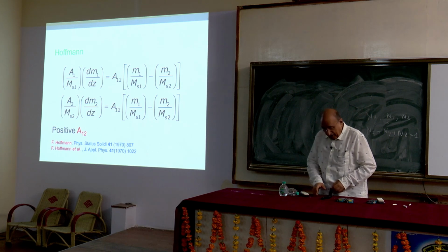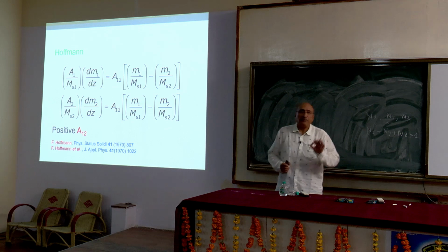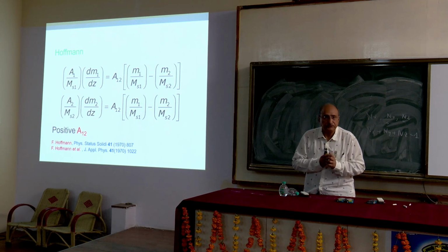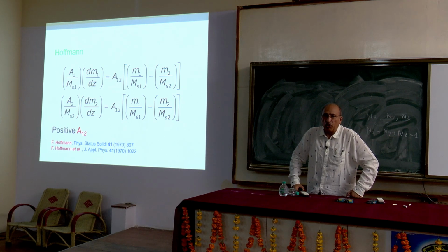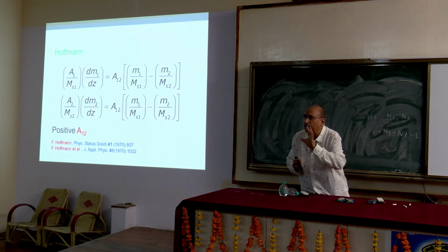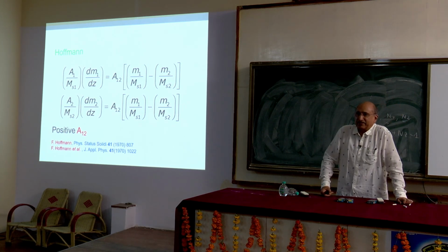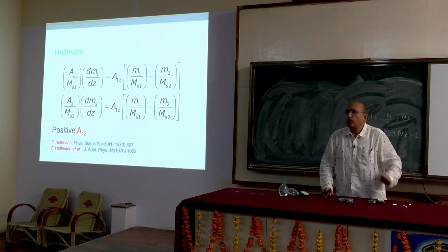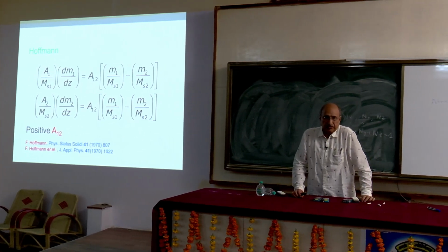which introduced another constant, A12, which is the interfacial anisotropy. Our boundary condition did not have any interfacial anisotropy constant. That was the deficiency of our boundary condition, because the coupling between the two films I could not manipulate using those boundary conditions. They were assumed always to be perfectly coupled. Now here there is a parameter A12, which you can adjust to set how strongly the films are coupled to each other.